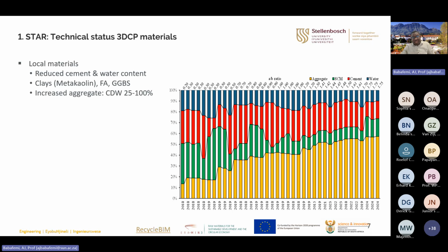respect, reducing the cement content and water content significantly, using cement extenders such as fly ash, slag, and then metakaolin. Not only that, we have also increased the aggregate to binder ratio. If you see the graph that you have here between 2018 to where we stand, or last year, 2024, you can see an increase in the aggregate to binder ratio. The last three publications here are from Stellenbosch University.